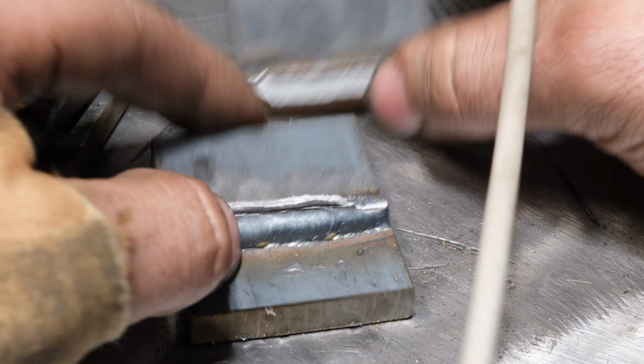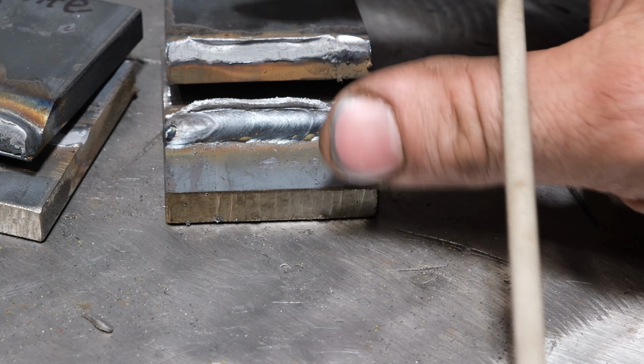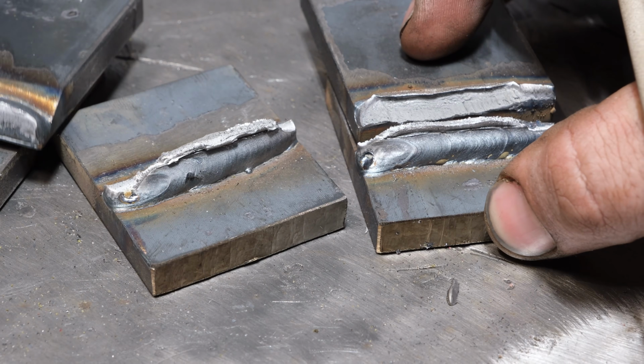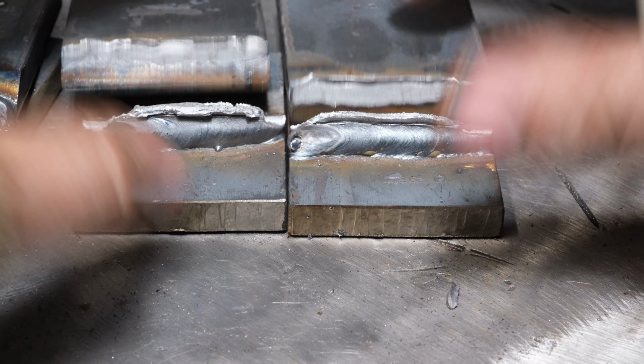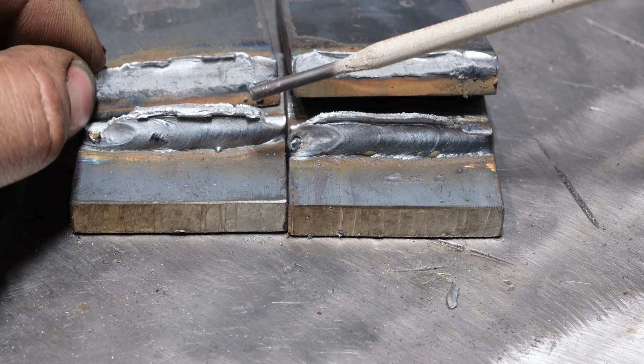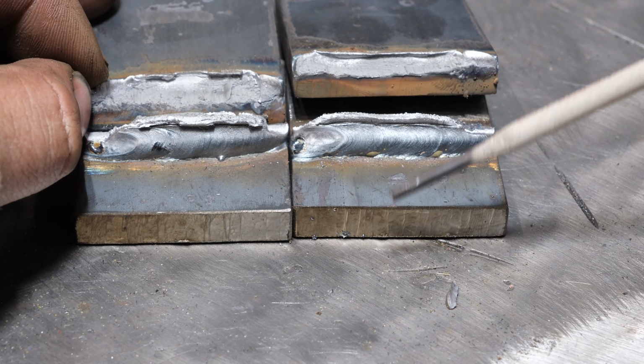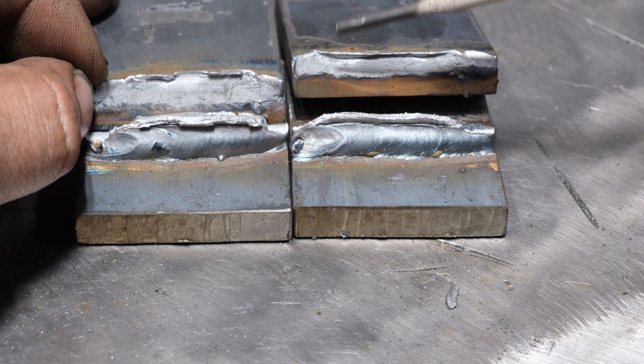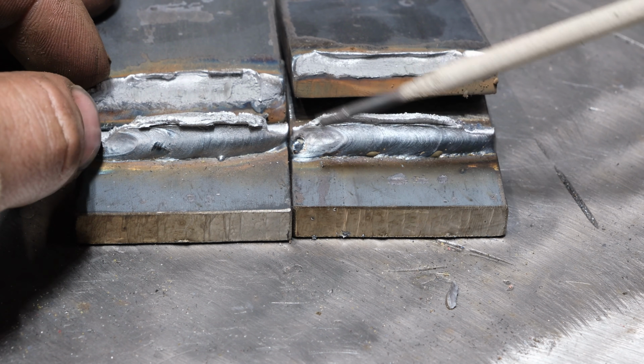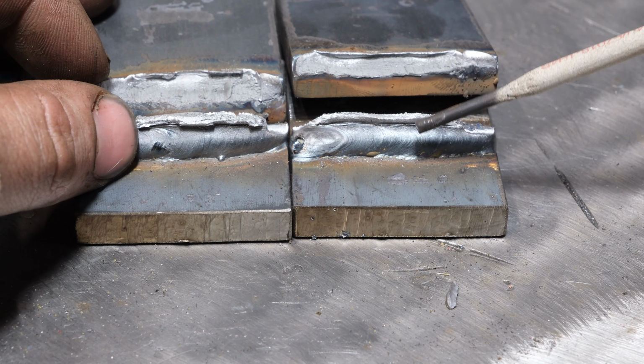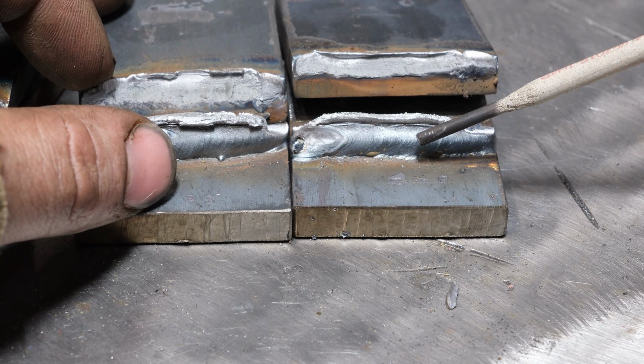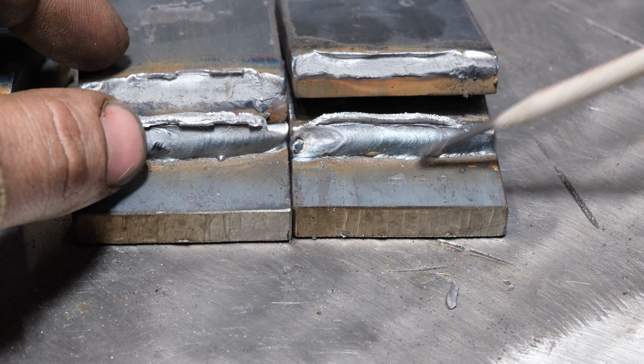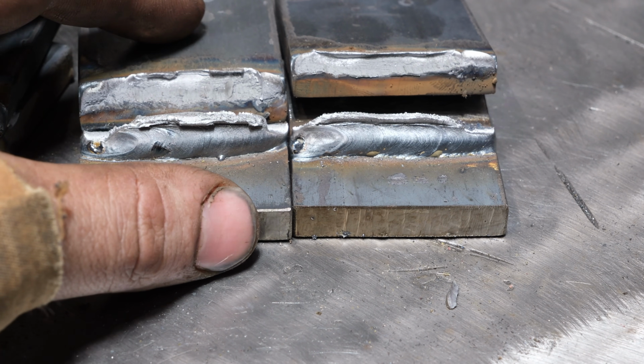So this, again, fairly high strength, and the reason for that high strength, really, just like this guy, the medium bevel, the more that you can get a weld to fuse to both the top and the bottom plate, the better your strength numbers are going to be. Anytime you have poor fusion into one of the two plates, you're going to have issues where it's going to want to pull off of that weaker penetrated plate. All right, that's enough of this. Let's look at the 140 amp.